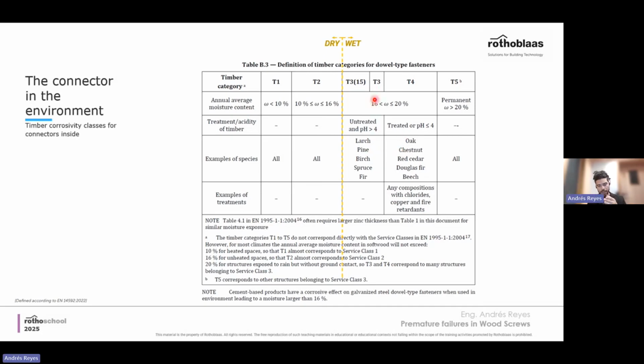So the norm states that from 16% at least, the type of species becomes relevant in the environment inside the wood. And that, of course, will affect the type of fastener that you should use to withstand that condition. The other important thing here is this is the service threshold. So we understand that from 16 above, the aggressiveness of the wood starts being relevant. And that means that if the construction conditions where the wood is exposed could lead to an environment that can lead to corrosion, that can then lead to the generation of hydrogen.